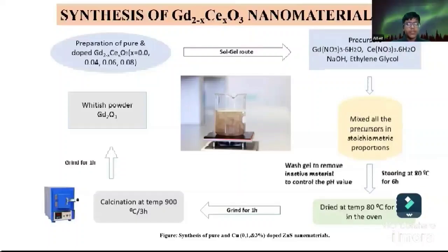Briefly speaking, gadolinium nitrate hexahydrate was dissolved in ethylene glycol, and separately NaOH, or sodium hydroxide, was also dissolved in ethylene glycol, and they both were stirred at appropriate temperature. Subsequently, the NaOH solution was slowly added to the precursor solution in order to maintain an optimal pH of 10. The solution was then heated at 110 degrees Celsius for 1 hour and further stirred at room temperature for 1 hour.